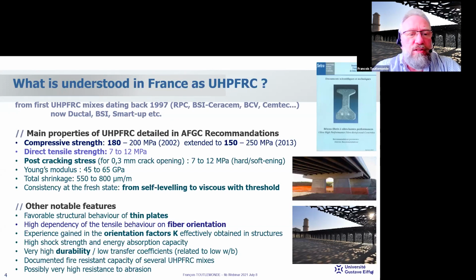The Young's modulus is between 45 to 65 gigapascal, the total shrinkage from 550 to 800 micrometers per meter. And the consistency at the fresh state is from self-leveling to viscous with threshold.